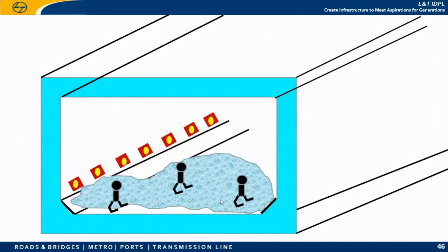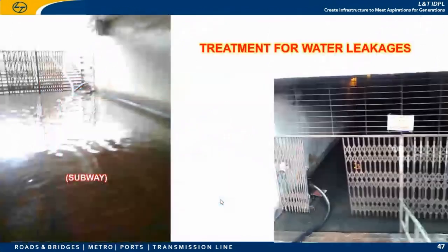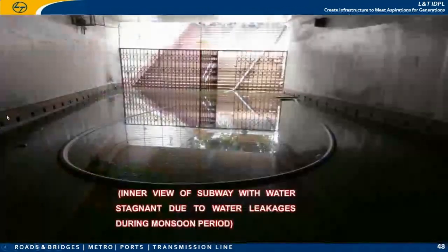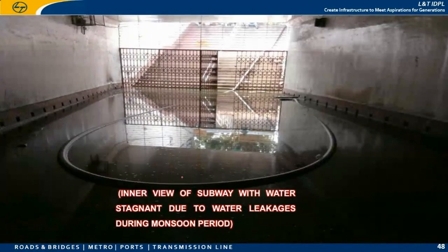First, as I told you, the engineer involved in this treatment procedure has to understand the problem and identify the source, the root cause of the problem. Then he has to map it. Then he has to apply a suitable method and a suitable material. The root cause here is that along the construction joints, the water is seeping or dripping inside. This is the view of water stagnant inside. Now you see, all along the side wall, the locations have been mapped.